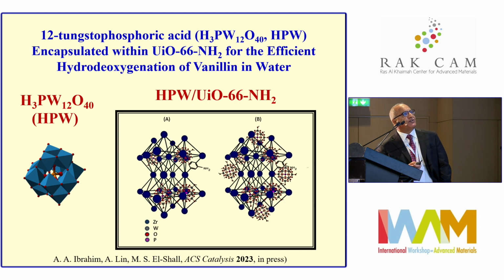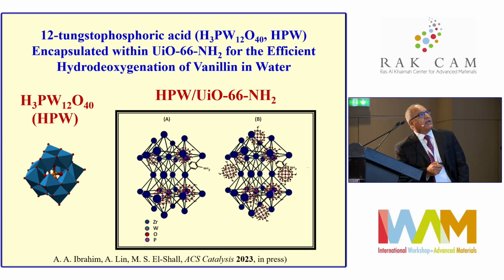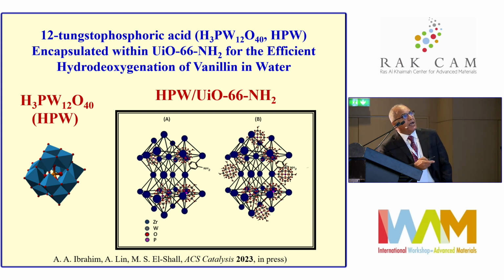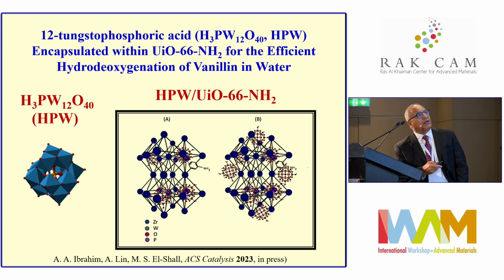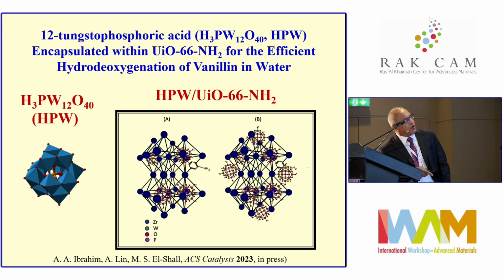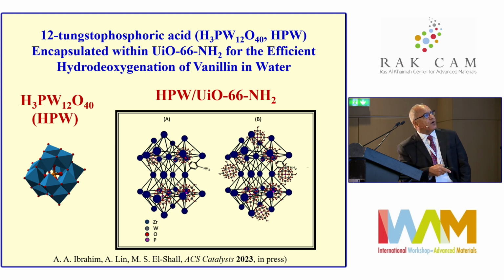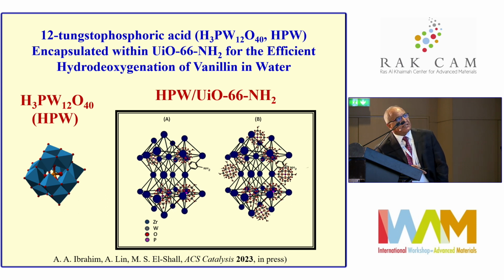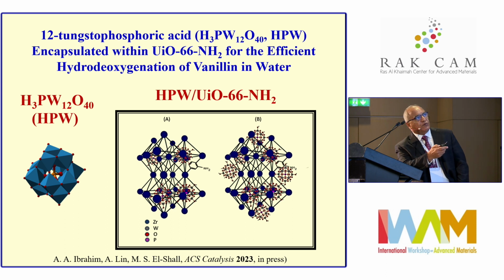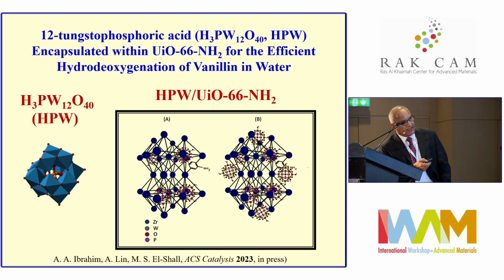The last system for the same reaction is incorporation of tungstophosphoric acid, H3PW12O40, encapsulated within UiO66 amine for, again, the hydrodeoxygenation of vanillin in water. So this is the solid acid, which is known as HPW, or tungstophosphoric acid, and it has very strong acid properties, and if it can be incorporated within the UiO66, that provides very strong acid sites, which is required for this reaction. So you can see with the palladium catalyst, you can achieve very high activity in this case.